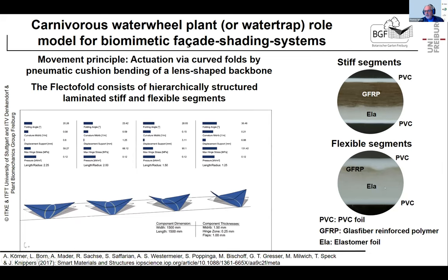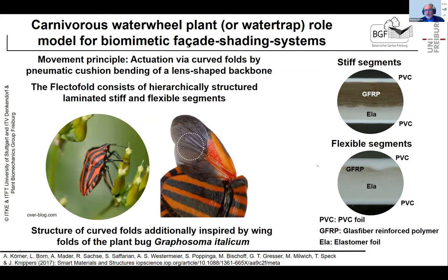We had one problem after several hundred motion cycles. The curved folds showed fissures. And this is no good, because for an application in architecture, the opening should be possible at least 15, 20,000 times without any failure. And for that, we had to optimize our curved folds. And this we did together with colleagues from Tübingen, who are specialists in wing folding and unfolding.